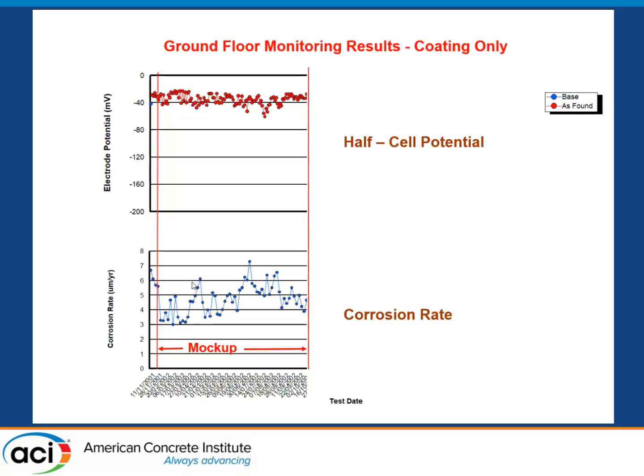And you can see a lot of erratic behavior in the corrosion. And just for relevance here, generally 2 microns per year would be considered low, which is this area here. If you're between, say, 2 to 5, that's kind of moderate. 5 to 10 is high, and then once you're above 10, that's very high. But these results just show the erratic behavior of the coating really trying to cope with the corrosion.